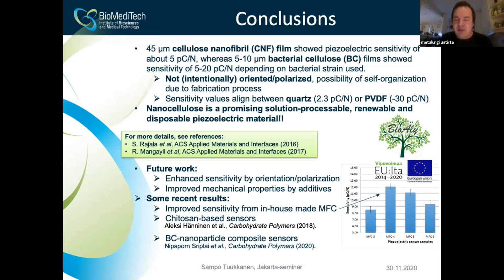Bacterial cellulose is a high purity material because it doesn't produce anything else but the bacterial film. And bacterial cellulose is also used for medical applications because of its high purity. In wood cellulose you can have some residues from lignin or whatever because it's processed from wood and contains other things. That can be one reason for the higher sensor sensitivities in comparison to wood based. That could be compared by intentionally adding some impurities to the nanocellulose to see how it affects this.